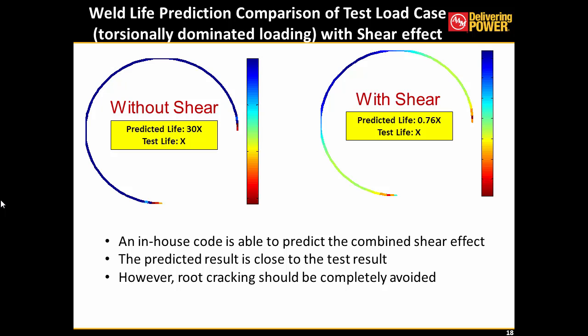Also, I forgot to mention, we need to consider that this is a throat failure, not the usual way of predicting through the thickness. So we need to understand that this was done through the throat of the weld, not through the thickness of the weld. If we look through the thickness, it will not give you very reliable results or results close to the test results. So depending on the failure mode, we should be able to model the weld.